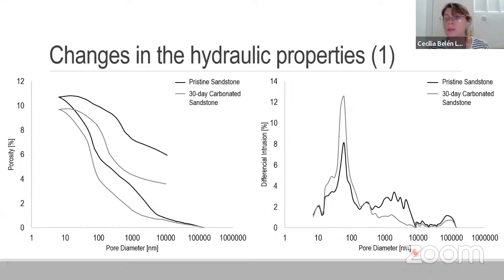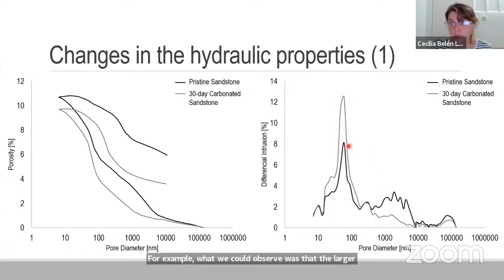But after carbonating our sample, we could observe that the larger pores were notoriously reduced, while the amount of small pores increased also notoriously.